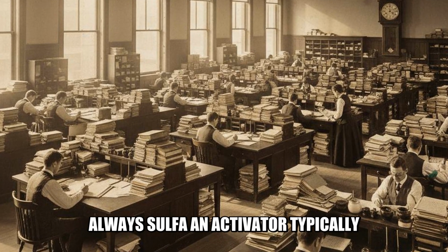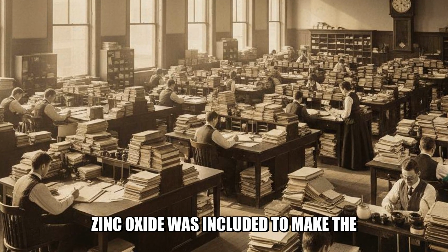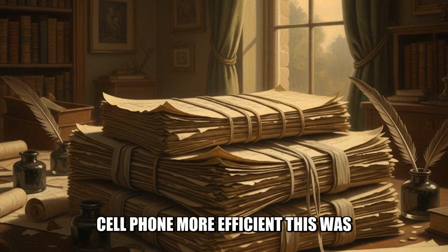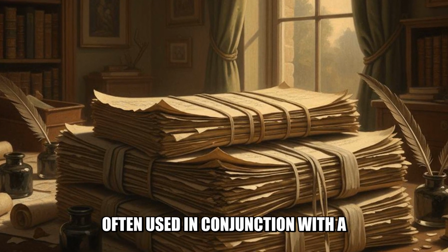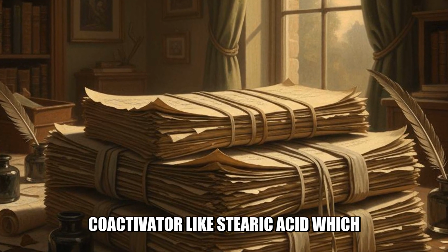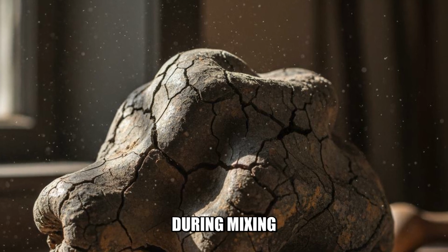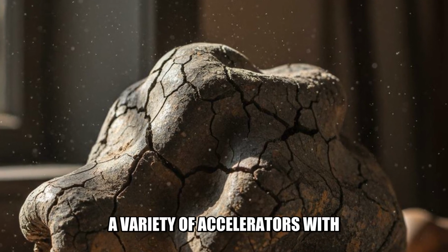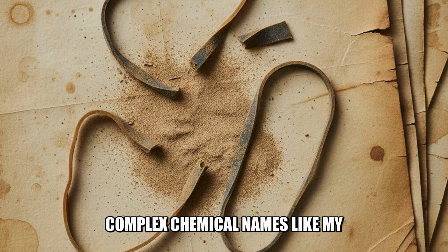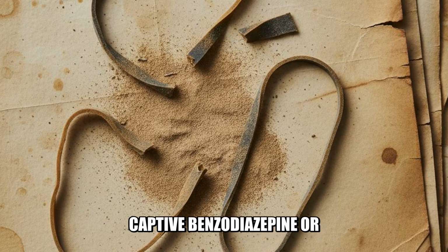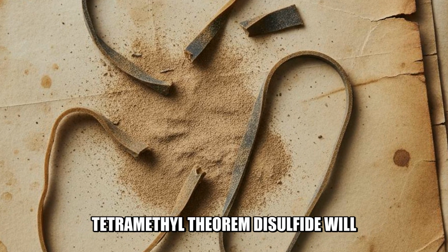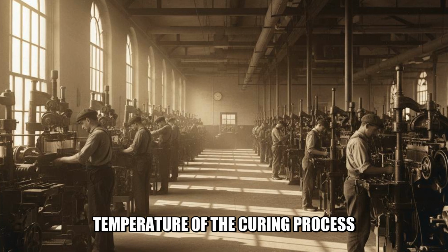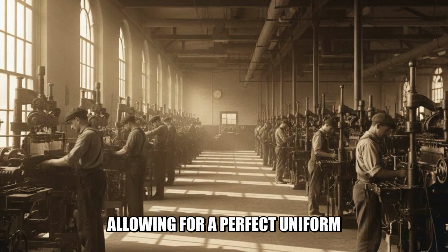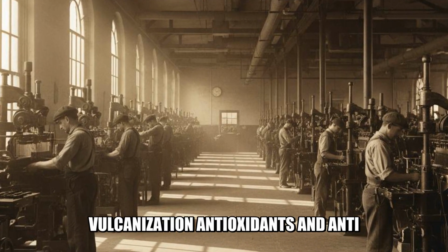An activator, typically zinc oxide, was included to make the sulfur more efficient. This was often used in conjunction with a co-activator like stearic acid, which also helped to soften the rubber during mixing. A variety of accelerators, with complex chemical names like mercaptobenzothiazole or tetramethylthiuram disulfide, were used to control the speed and temperature of the curing process, allowing for a perfect, uniform vulcanization.